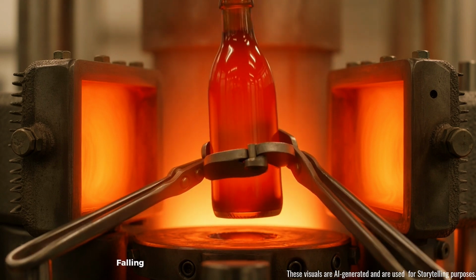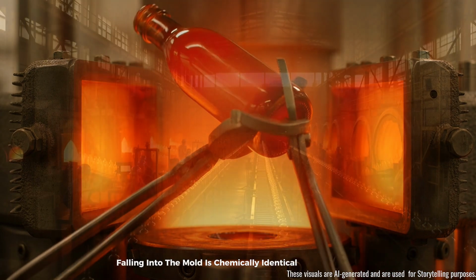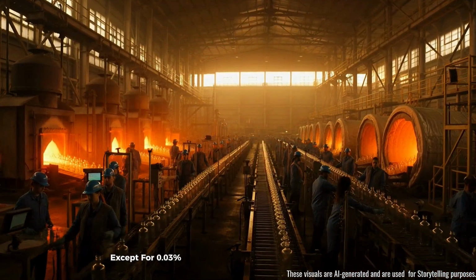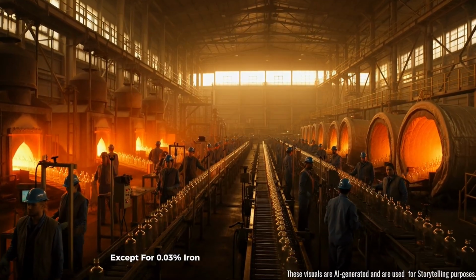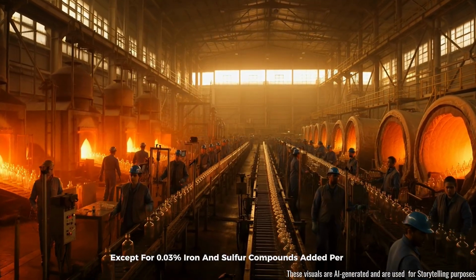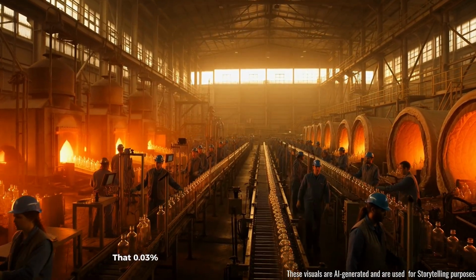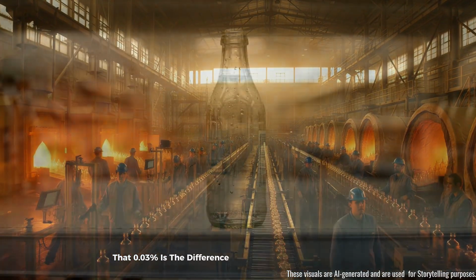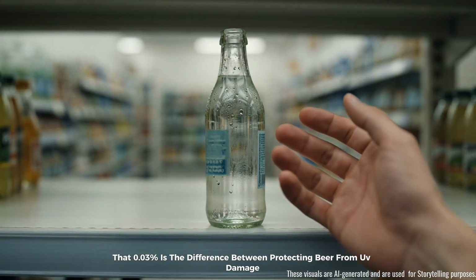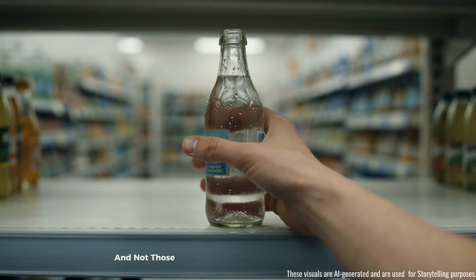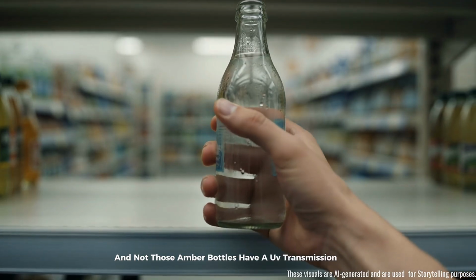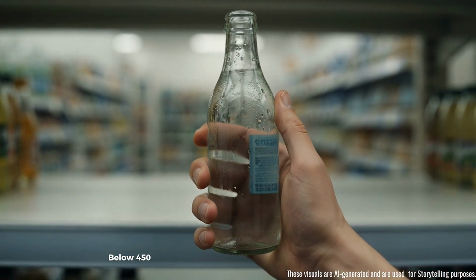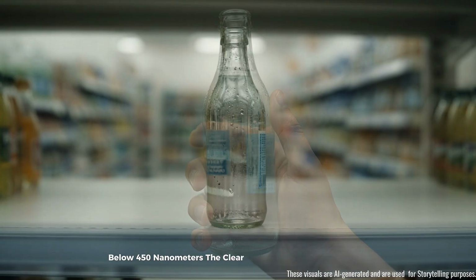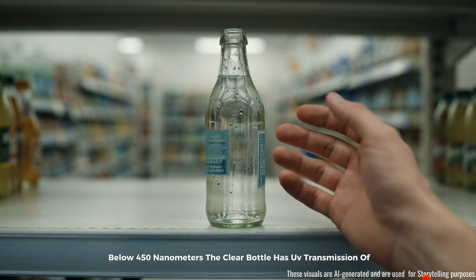The amber gob falling into the mold is chemically identical to the clear gob, except for 0.03% iron and sulfur compounds added per ton of batch. That 0.03% is the difference between protecting beer from UV damage and not. Those amber bottles have a UV transmission of less than 1% below 450 nanometers. The clear bottle has UV transmission of 90%. The color is not aesthetic, it is functional chemistry.